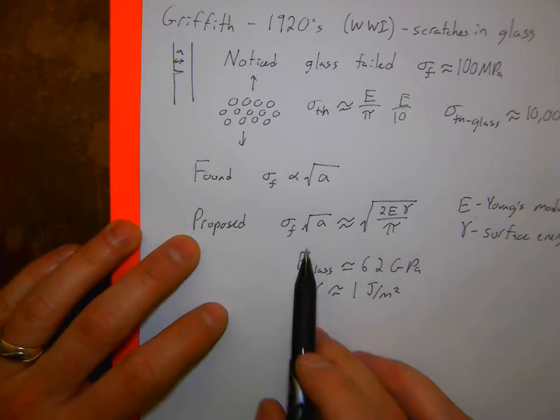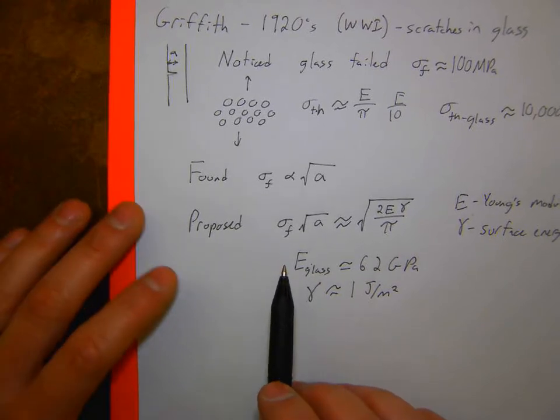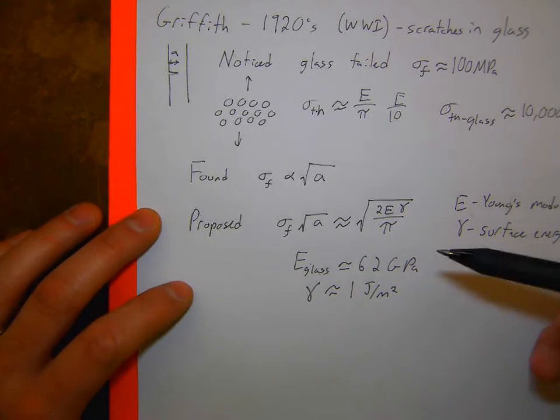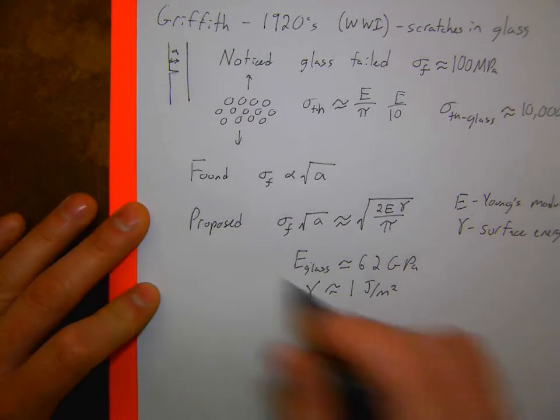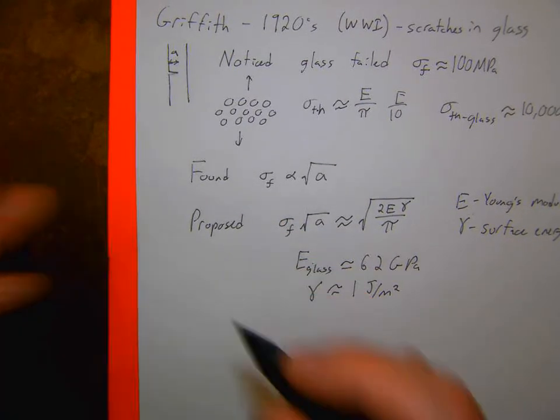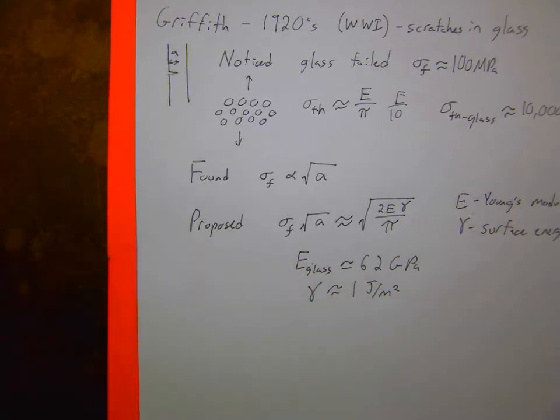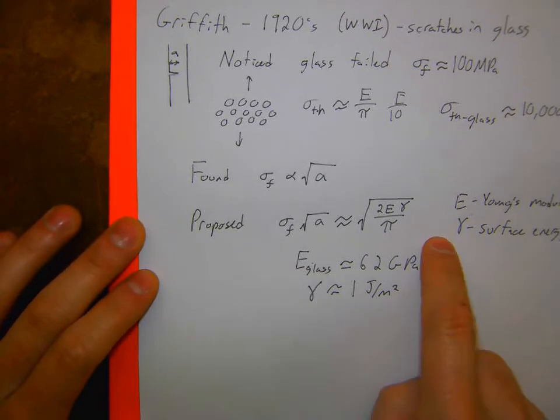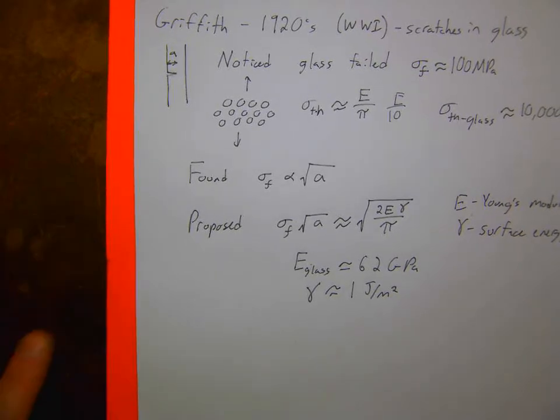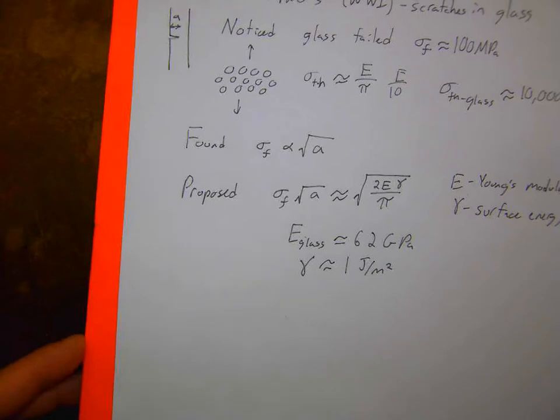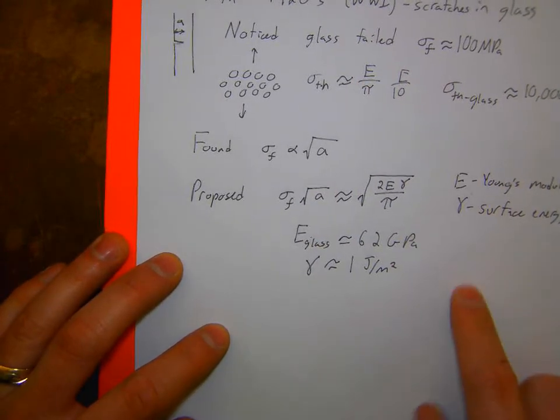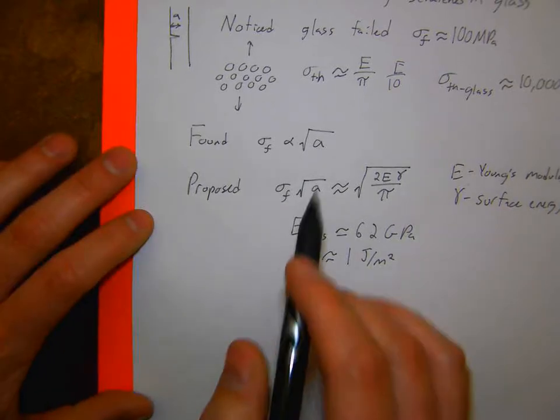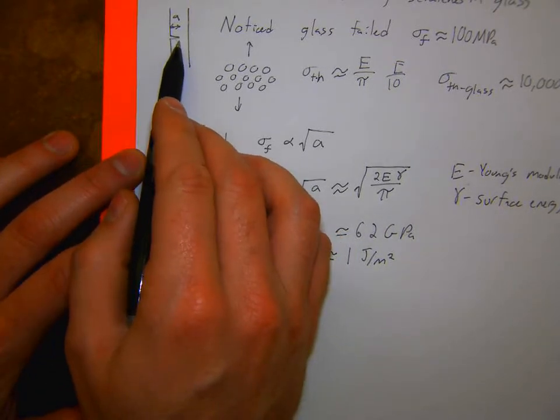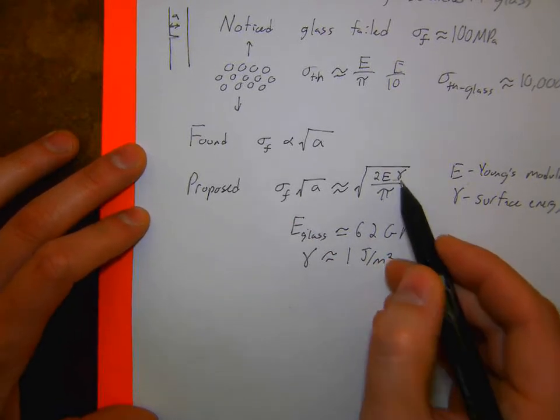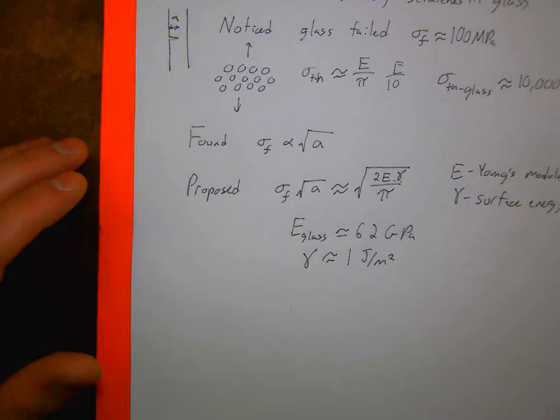And so from that, he was able to obtain a reasonable prediction of what the fracture strength of glass was, because he said, when you crack these things open for a brittle material like that silicon wafer that we saw, all of that energy is just going into forming those two new surfaces. And so for a brittle material, this is actually a pretty good approximation. The problem is most of our engineering materials aren't necessarily brittle. But this was historically when it first started getting looked at. And so now the bigger the scratch is, the weaker the material is, and all of that is from this theory due to it taking less energy to form a new surface.